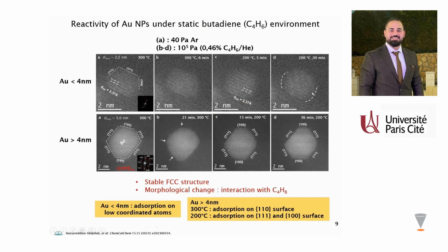a change of its morphology to a rounded morphology at 200 degrees Celsius, but without any transition of the crystalline structure. However, in the case of the bigger particle having a size of 5 nanometers, we have a temperature dependence of butadiene adsorption on the gold nanoparticle.